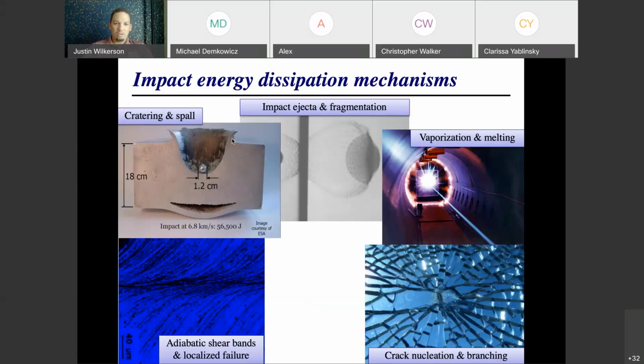In this case, the target material is actually thick enough that it stops the projectile. So the projectile burrows about halfway through the target material, but it doesn't penetrate. So in that sense, the projectile has stopped, or the target has stopped penetration. And if we think of this as an armor material, then it kind of did its job in that sense.